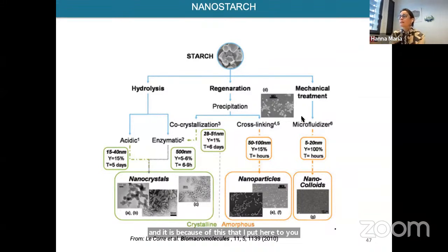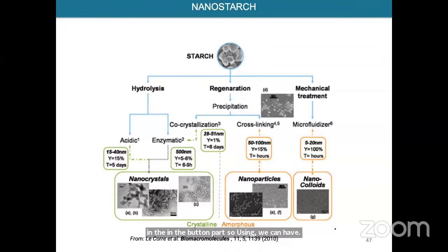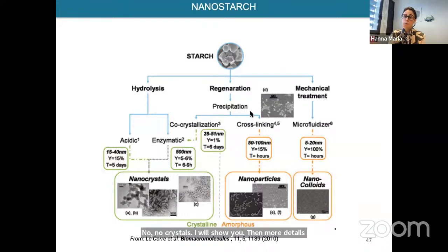So we have three main ways to obtain starch nanoforms or nanostarch. We can have starch nanocrystals, as you can see here in the bottom part. Using hydrolysis, we can obtain nanocrystals. I will show you more details about it later. If we do some precipitation, we can have what we call starch nanoparticles. And if we do mechanical treatment, like I told you before, not to have nanoparticles but to be able to dissolve starch easily, we can have what we call nanocolloids.